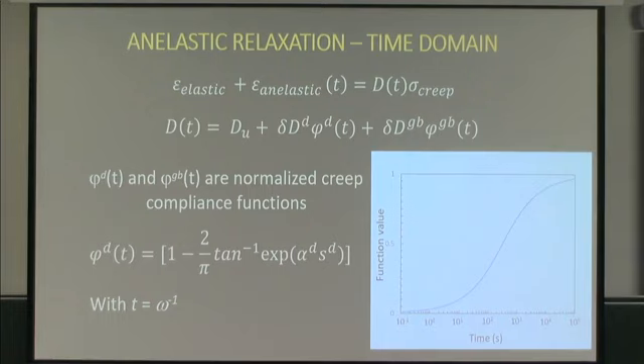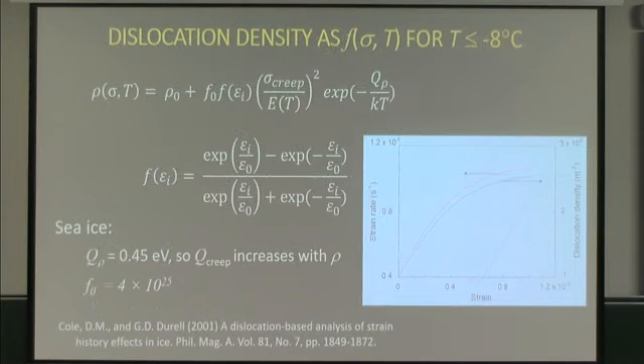And here's our function. Basically, it's the storage compliance function that works perfectly for this 0 to 1 behavior we're looking for. So in time, for each of these mechanisms, the strain is realized according to that function and according to that strength. So pretty straightforward. The other thing we're able to do is the dislocation density gets determined experimentally.